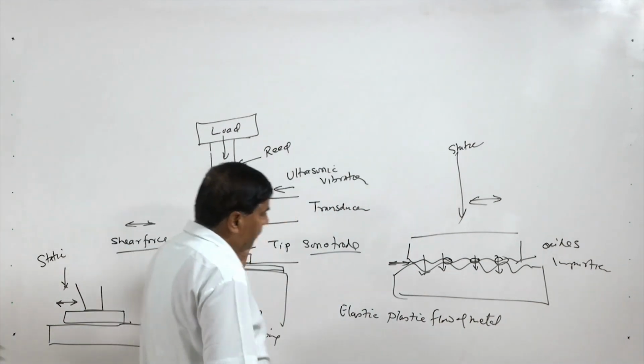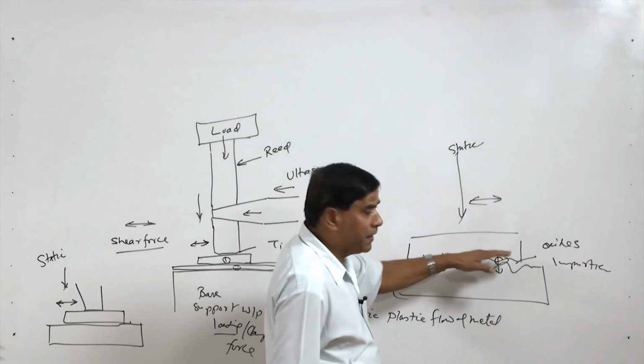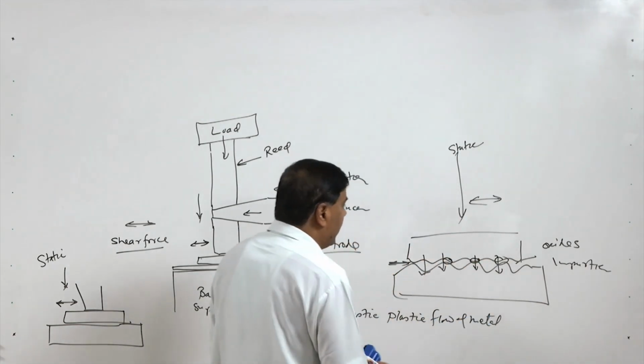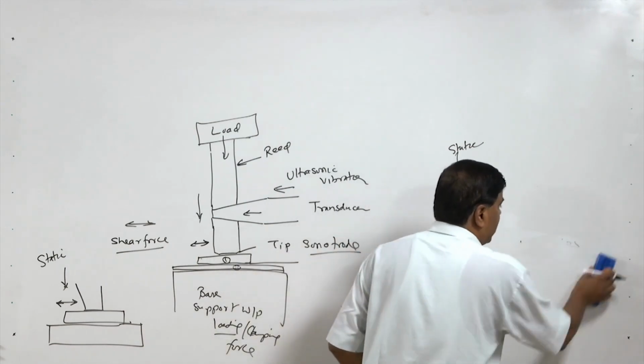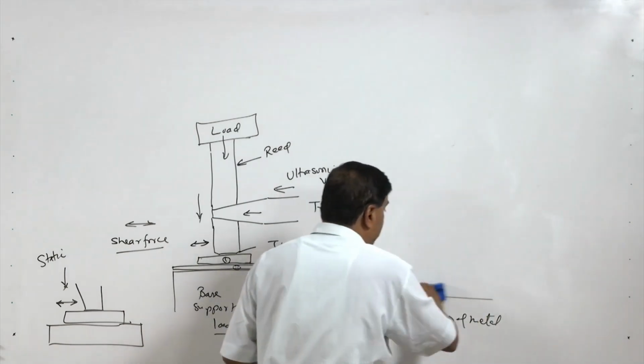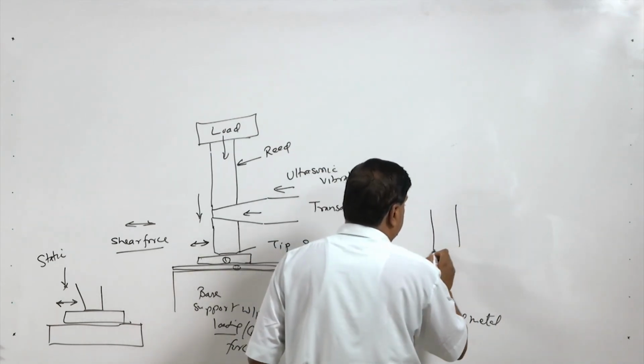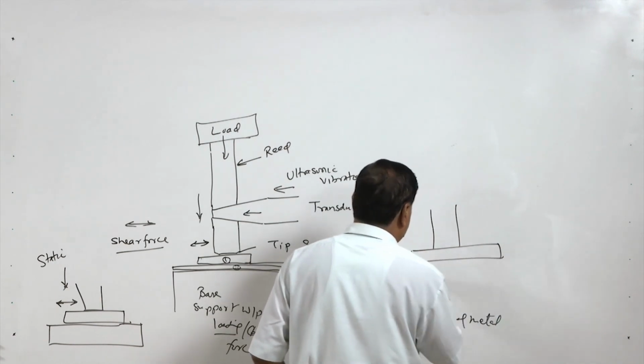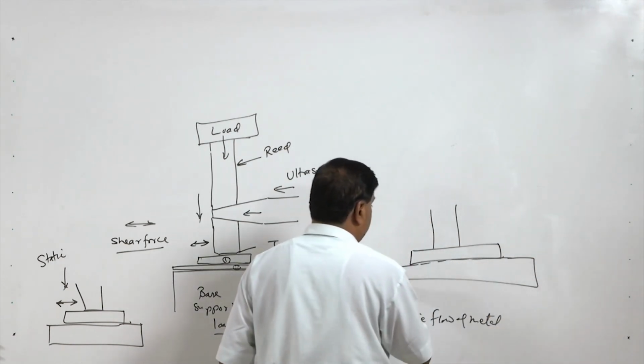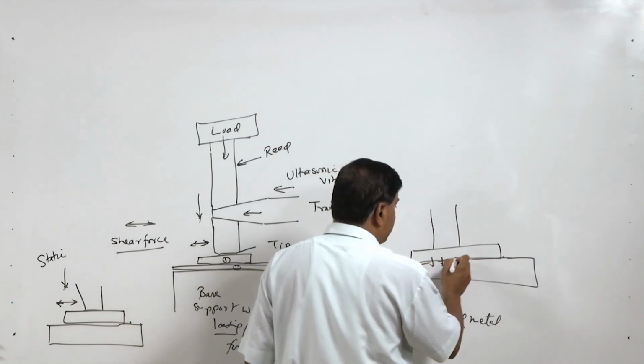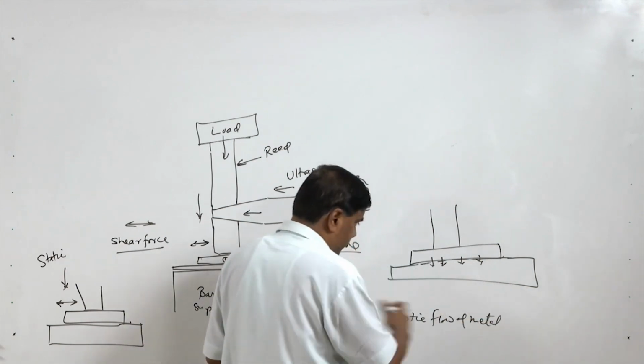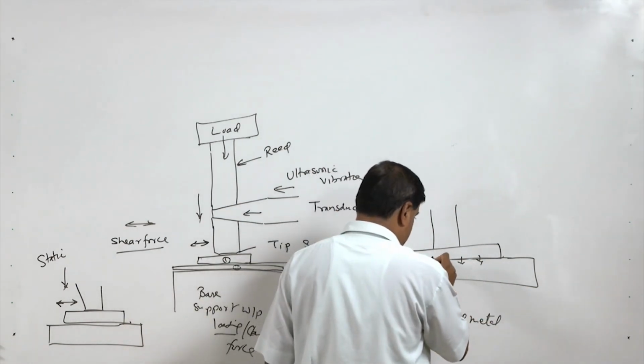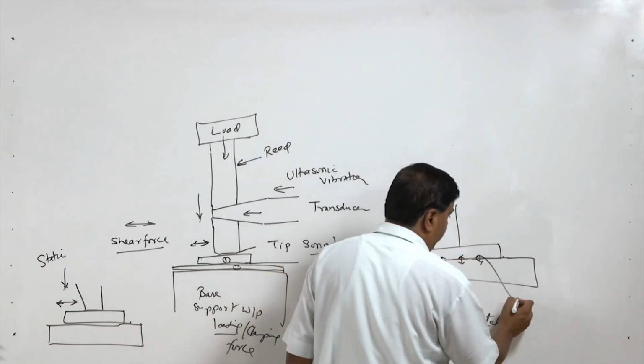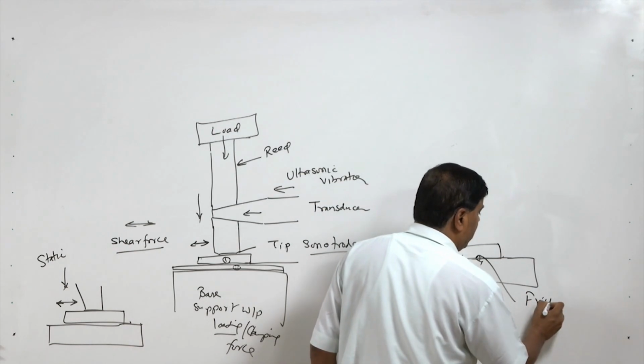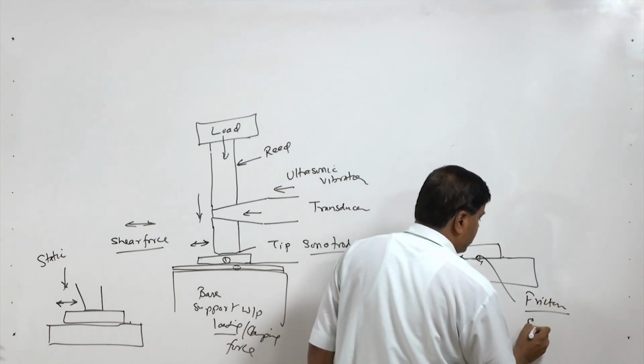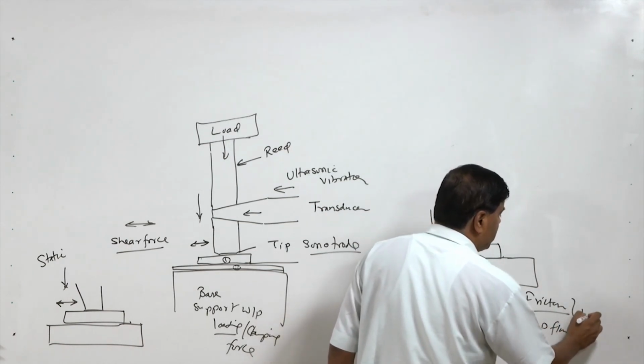As the process continues, elastic plastic flow at the interface will continue to increase, and this in turn will keep on increasing the direct metal to metal contact area, and subsequently the contact between the two pieces to be joined is perfect. Under this condition, what will we see? Due to the elastic plastic flow of the material, especially at the interface, what are the things involved? The friction and elastic plastic flow. All these things will generate enough heat.